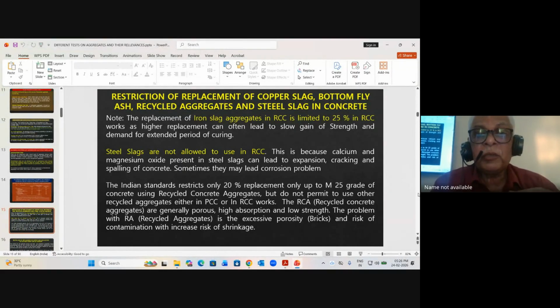Indian standards also restrict 20% replacement only up to M25 grade concrete using recycled concrete aggregates, but do not permit recycled aggregate to be used in either PCC or RCC work. RCA means recycled concrete aggregates, which are generally porous, have high absorption, and low strength. The problem with recycled aggregate other than concrete is porosity, risk of contamination, and high risk of shrinkage. That's why they're not allowed to use in some cases.